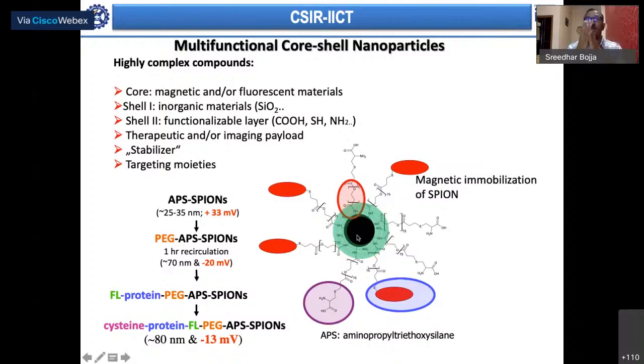If you want to see a change in the material, you can have a fluorescent material as the shell. Or if you want to make the whole thing magnetic, a core shell magnetic nanoparticle, you can have the core as magnetic, and the whole thing becomes magnetic, so you can use it for various magnetic applications. Depending on that, you can have inorganic material as the shell, which can be silica or titanium, whichever is of your interest. Then you can functionalize it.